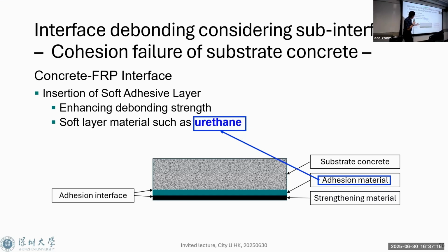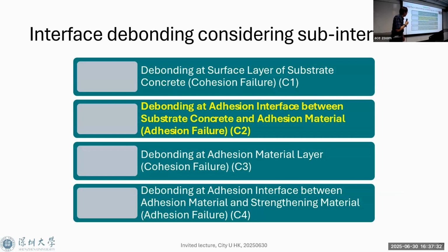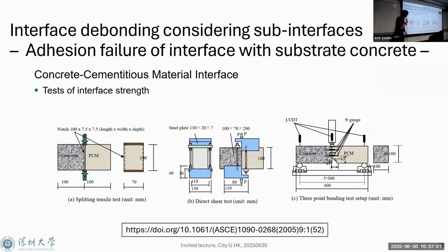Then, knowing this fact, some technology was developed using quite a low thickness of the adhesion layer, such as resin, so that you can have higher debonding strength. So a softer adhesion layer is one way to increase debonding strength. Then comes another debonding failure mode: debonding at the interface between the substrate concrete and the adhesion material. So we have another study looking at the bonding strength here for cementitious material failure.